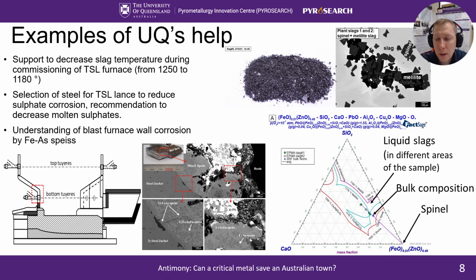Over the years, our research group had many projects to help Nyrstar, particularly to optimize the operations of the newly installed TSL furnace. As I mentioned before, the furnace is designed to produce molten slag. In the beginning, the focus was on the achievement of design productivity, and the recommended slag temperature was about 1250 degrees Celsius, ensuring it is fully molten, low viscosity, and dissolves feed materials very fast.